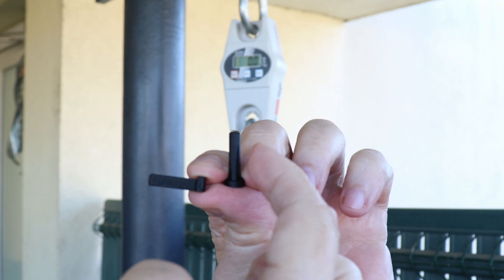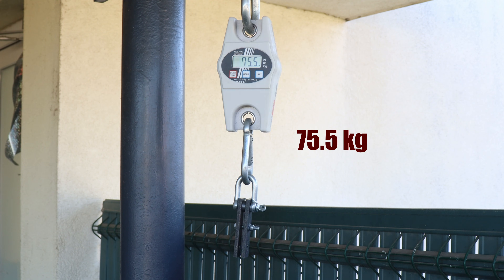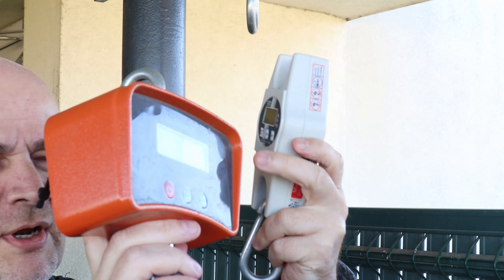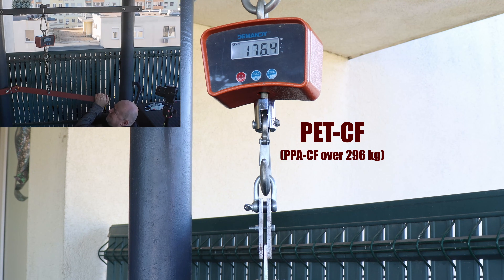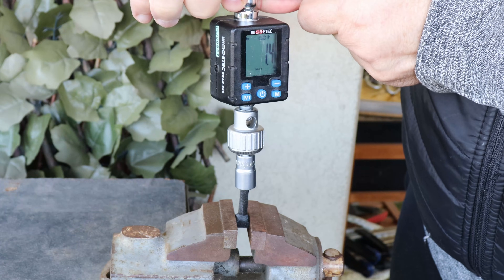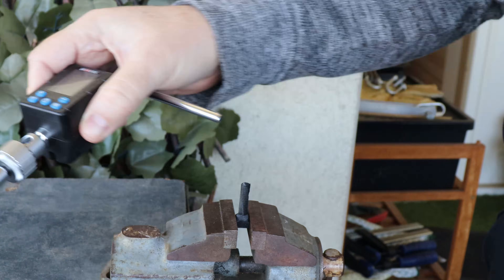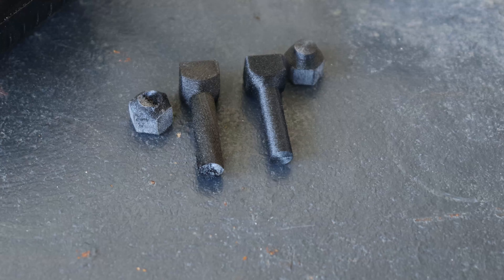For shear tests I have horizontally and vertically printed test objects with the same dimensions. Starting with vertically printed where layer adhesion is important. Now switching to the crane scale which has a maximum of 500 kilograms — extremely strong in horizontal direction. Torque or twist test with horizontally and vertically printed test objects. For horizontally printed I record the load at 90-degree rotation and the maximal load — they were equal here. Vertically printed usually snaps suddenly so I can record only the maximal load. Very similar numbers but a different type of break — vertically printed breaks more suddenly.